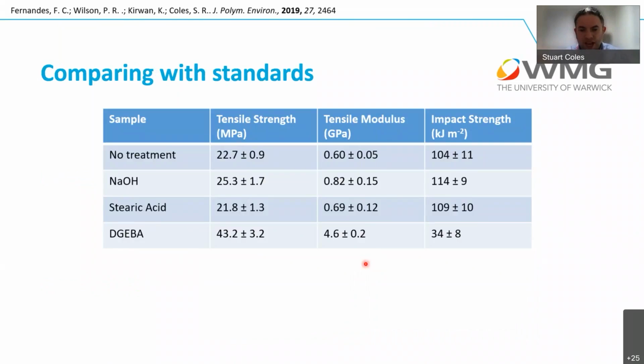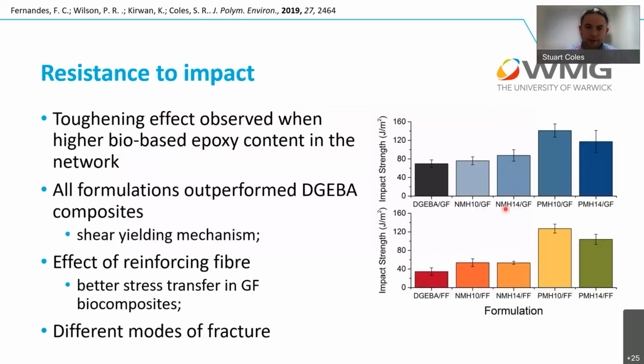We compared that with the standard, and you can see straight away why our thinking was in this area. Just the standard DGEBA, tensile strength was much higher, tensile modulus was much higher, but the impact strength was much lower. And we'd identified materials that had a really good impact strength, and this was where we should be focusing our mechanical testing. It shouldn't be around making materials that are the strongest and the stiffest. Actually, energy absorption for us was definitely the way forward.